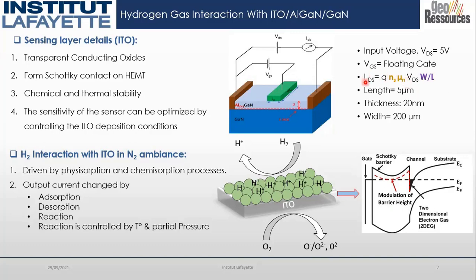Now, this output current IDS can be varied depending on two parameters: the geometry and the heterostructure of the device, and the gas interaction with the functional layer. For the geometry of the device, we keep the length 5 micrometer, thickness 20 nanometer, and width 200 micrometer. And this parameter will be varied depending on the interaction of the target gas.